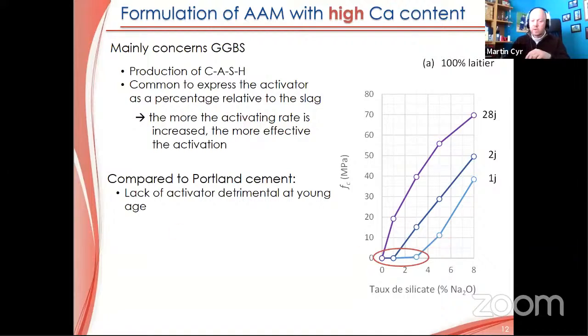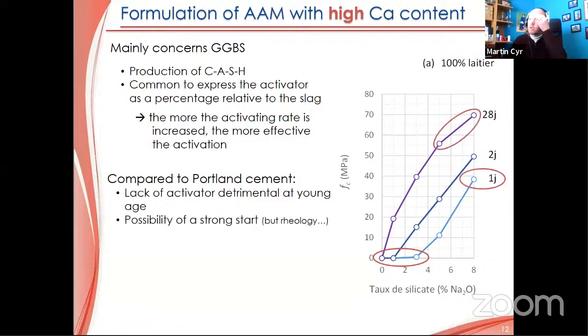Of course, as it was said earlier, we must check the overall cost at the end, but it's not always easy to discuss with an industrial partner who tries to have a look at the overall, but they are focusing a lot on the price of the materials itself. So sometimes we can have a very low reactivity at short term if we don't put enough alkali inside. We can have the possibility of a very strong start, meaning that if we put 8% of equivalent sodium inside, we can have up to 40 MPa at 1 day, which is quite good when we compare it to a Portland cement.